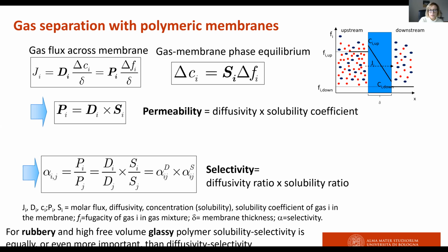And also you can introduce the permeability, which is the flux divided by the fugacity gradient. And there is also an equilibrium, a phase equilibrium at the interface between the membrane and the gas phase, which is governed by the solubility coefficient S. In the end, the permeability results as the product of diffusivity and the solubility coefficient. And the selectivity, which gives you the removal capacity of the membrane, also as a result can be decomposed as the product of a diffusivity-based and of a solubility-based contribution.